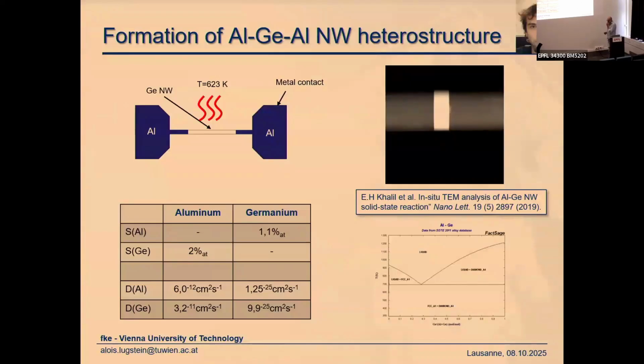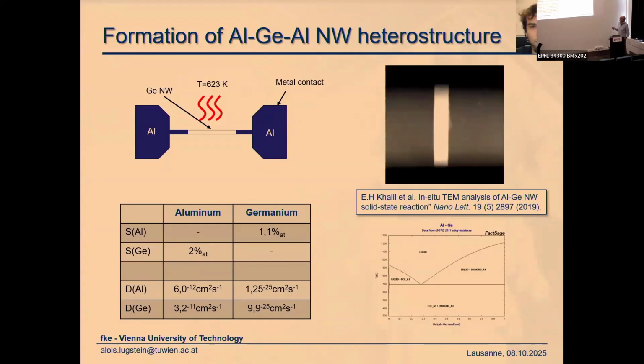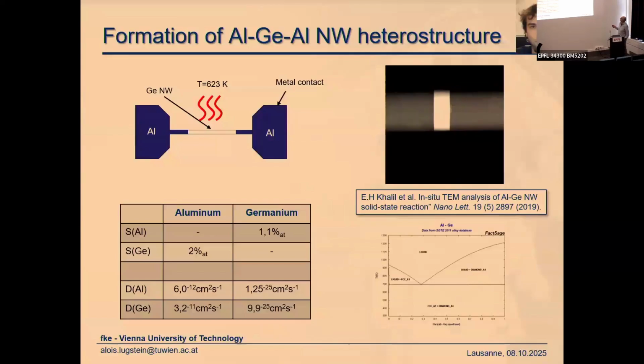So Sebastian Kral then tested a lot of materials. At that time, we were interested in superconductor, semiconductor, heterostructures. And finally, we ended up with aluminum. So very same story, germanium nanowire, 2 aluminum contacts. And what is shown here is again an in situ movie of this exchange mechanism. So this is a germanium segment.